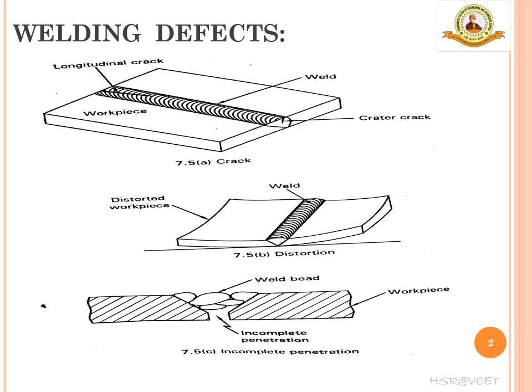The second type of welding defect is distortion. As you can see in figure 7.5b, it is called distortion. Distortion is the change in the original shape of the workpieces after welding. As you can see, instead of being flat, it has raised to a certain angle. The causes are high residual stress due to shrinkage, high heat input, multiple number of passes, and low welding speed.